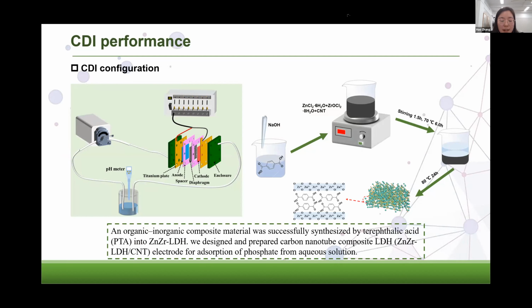In this study, an organic-inorganic composite material was successfully synthesized by intercalating terephthalic acid into zinc zirconium layered double hydroxide to maintain the traditional properties of porous electrode material. We designed and prepared carbon nanotube composite LDH electrode. Here you can see the two figures which show you the capacitive deionization device and the process of material preparation.